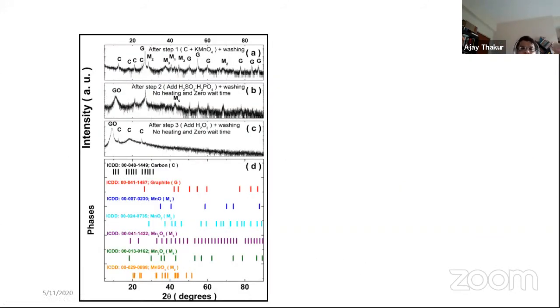So for researchers entering into this field or a related field, it is important to not ignore simple techniques like X-ray diffraction. Right, so X-ray diffraction has a lot of strength in helping you try to decipher the mechanism of reaction and so on, and that is what we employed it for. So what we did was, after each sub-step of our reaction, we would try to wash the product, and then we would take XRD and see what stage the reaction is in. So there were many more intermediate XRDs. I am showing 3 for representative purposes.